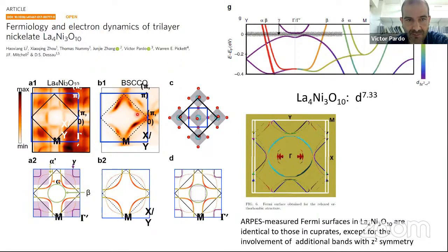These are the d x squared minus y squared of the cuprates, and you have those similar Fermi surfaces plus many additional features, because you are far from the filling that is interesting to compare it with the cuprates. But you do see some parts of the Fermi surface that resembles the physics of the cuprates.